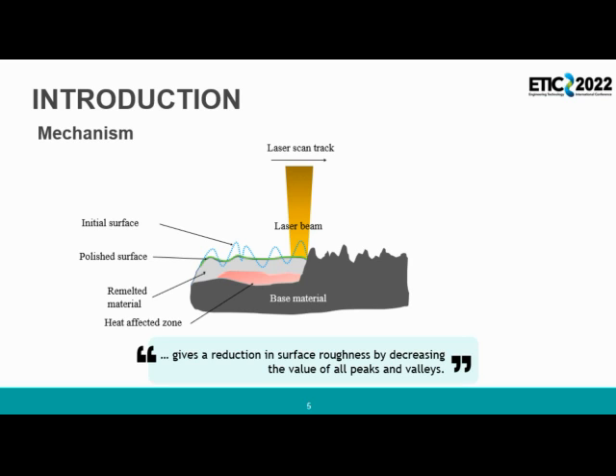A melt pool is formed by the absorbed laser beam as it moves across the surface at a specified scanning velocity, melting new material on one side and solidifying it on the other side. The surface roughness of the molten material is smoothed out during the process of remelting as a result of the surface tension of the material.